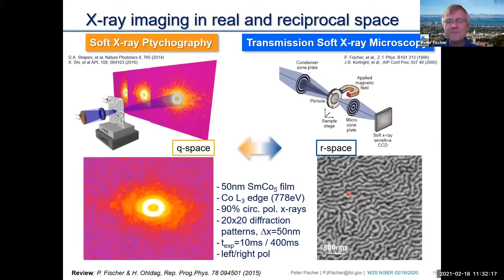So here's just a comparison. A full field soft X-ray microscope that I've been using a lot, and I think Suprankar also remembers at the time when he came to Berkeley, where we just put the sample into the beam, and you have a setup similar to an optical microscope. There's the X-ray source, a condenser zone plate focuses down onto the sample, and there's a micro zone plate that generates an image onto a CCD camera, and within a few seconds you get an image of the domain pattern, where, as you can see here, black and white areas mean your magnetization, because we're using XMCD as the contrast mechanism. Black and white means the magnetic moments at this location point in the forward direction, and the other, let's say, point in the opposite direction, or vice versa, depending on the polarization of the X-rays.